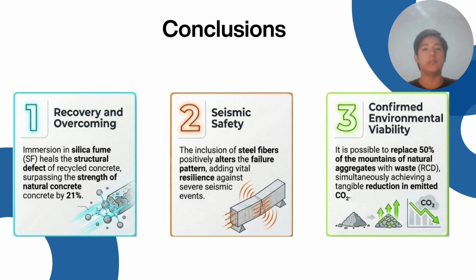In conclusion, this research demonstrates that recycled concrete aggregate can be successfully incorporated into structural concrete when appropriate treatment methods are applied. First, the silica fume slurry treatment recovered and even exceeded the strength of conventional concrete, surpassing it by 21%. The addition of steel fibers improved post-cracking behavior and structural integrity, adding vital resilience against seismic scenarios.